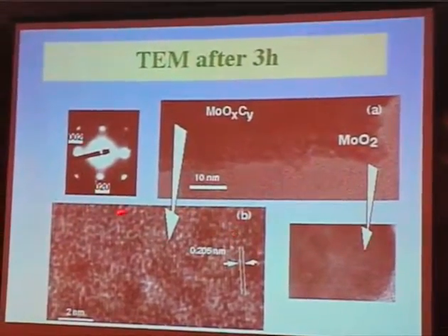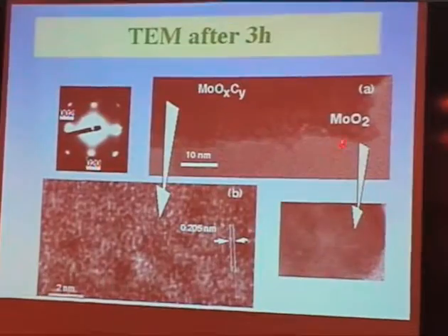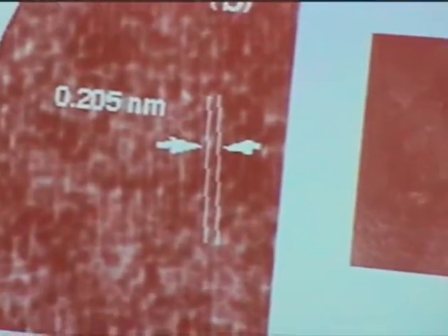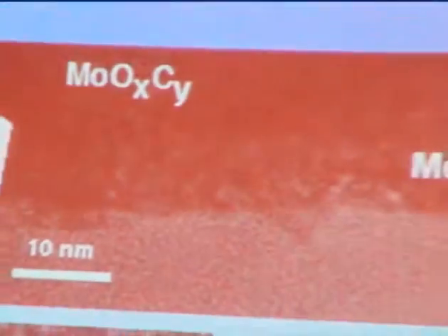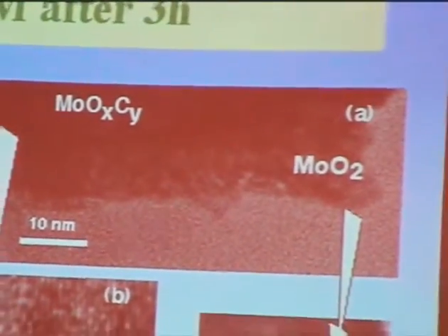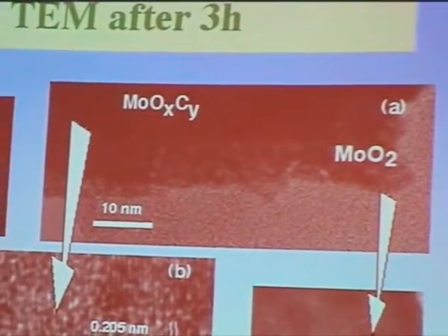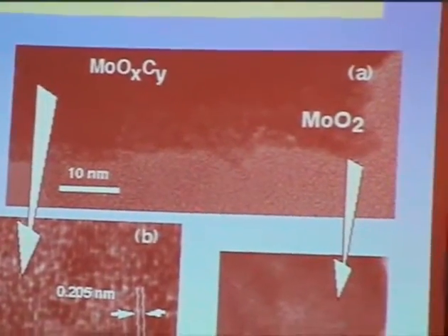So you see we have this order. There it's a less focused system. You have a sort of amorphous mass of oxycarbide. We call it already oxycarbide, even if it is not the final oxycarbide. Plus MoO2 crystals. These MoO2 crystals, you can see them very well there, and also by selective area electron diffraction. But this selective area diffraction is made on this carbide. And if you enlarge, if you increase the resolution, you see this very strange shape on it, but it is not the final product.